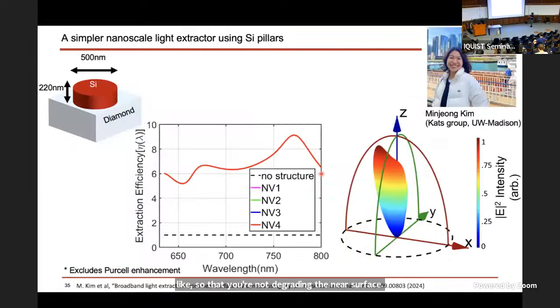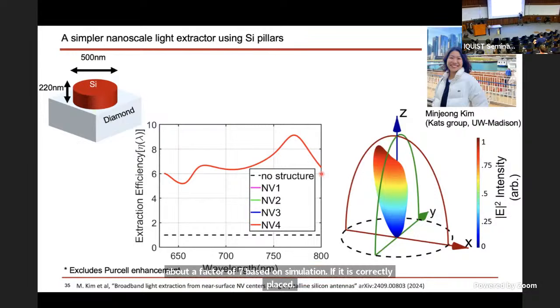So maybe skipping over this work, but talking about a recent experiment where we were able to demonstrate this with just a very simple silicon pillar that you can fabricate in place on the diamond surface. And this was done using a membrane transfer technique. What this silicon pillar does to near surface NVs is increase the extraction efficiency by about a factor of 7 based on simulation if it is correctly placed. And also it helps beam the light into a lower NA collection optic.